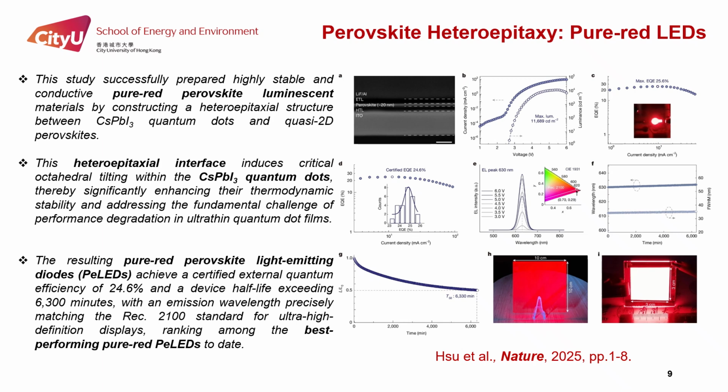The resulting perovskite LEDs achieve a record-breaking external quantum efficiency of 24.6% and a significantly extended operational half-lifetime of over 6,300 minutes, making it one of the top-performing pure-red perovskite LEDs for ultra-high definition display today.